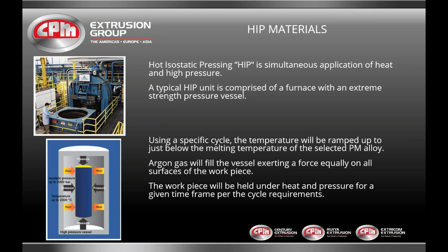With most of our powders, probably about 75 to 80% of them, the HIP containers are put into one of these vessels. The thing is sealed off. They ramp the pressure up to about 5,000 psi, then they ramp the temperature up to close to 2,000 degrees—it's below the melting point, still a powder at that point. Then they ramp the pressure up to about 15,000 psi, and it's held there for a certain length of time, then slow cooled and removed from the vessel.